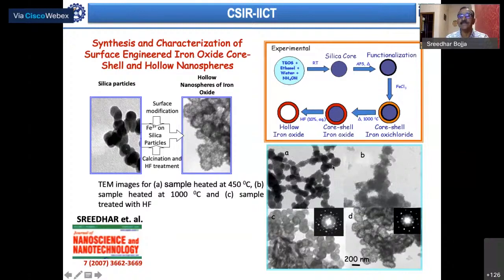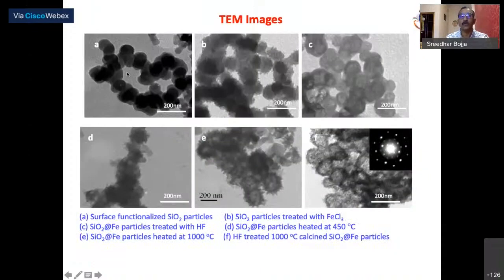We tried to measure at different steps of this reaction, and as you can see, initially you don't see the core clearly, but at the end of the reaction, the core is completely removed and you have only the shell material. This was after calcining at 1,000 degrees and treating with HF to remove the silica, so you can clearly see they are hollow particles of iron oxide.